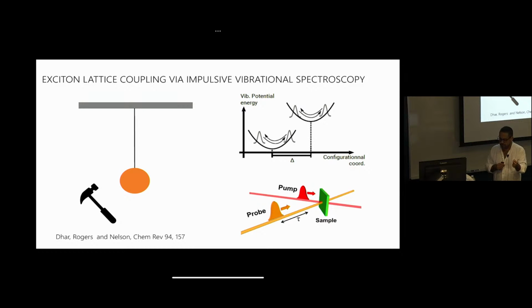You pump with a femtosecond pulse, then you take another white light probe, femtosecond probe, you transmit that through the sample, and you measure the changes in transmission induced by your optical pump. You've removed population from your ground state. You go from a valence band to a conduction band. You bleach away the valence band, and you see that through a change in transmission of the probe.